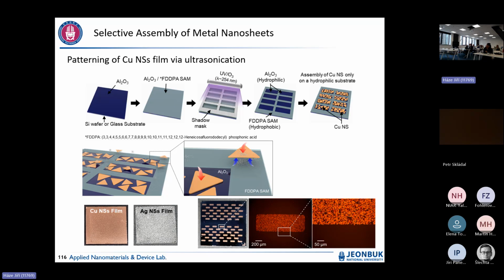Then we can control selective patterns by changing between hydrophobic and hydrophilic surfaces using a phosphonic acid self-assembled monolayer. For patterning, we just put our sample in solution, do ultrasonic, and get a really nice pattern without any further process. Because when you pattern any metal, you have to do a lithography process, or spray or inkjet printing, something like that. It is applicable not only to copper nanosheet but also to aluminum and silver nanosheet.